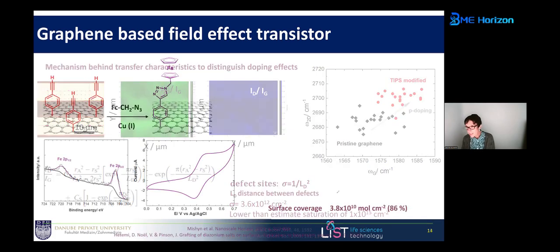So what that means is that probably we clean our interface of some polymer which was left on the surface with this diazonium radical chemistry, and therefore get very good characteristics for gFETs. Now you can ask me, what do we do with these diazonium modified interfaces? Well, if we use this TIPS chemistry, you need to deprotect the TIPS group. And when you do this, you end up with a triple bond. And every chemist will know triple bonds can now be integrated with click chemistry, and we used here an N3 modified ferrocene molecule as a model compound to show that it works.